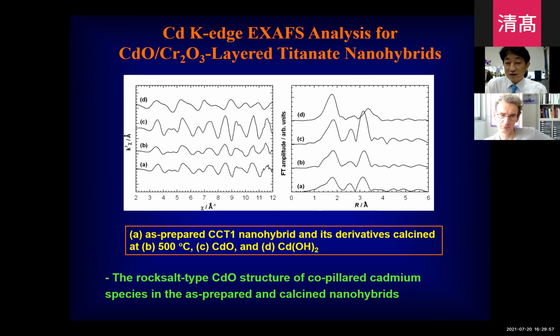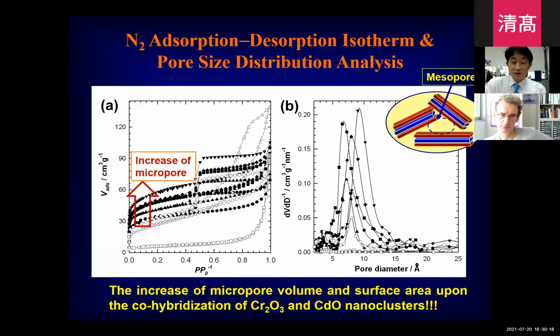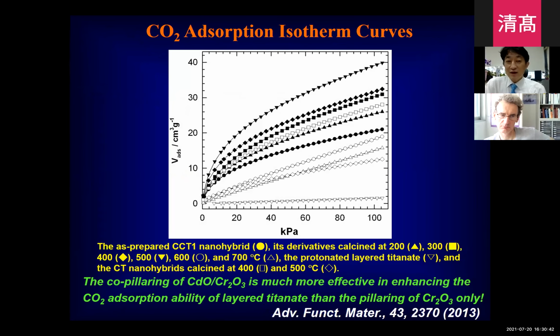Definitely, this FT structure is quite different from the cadmium K-edge EXAFS spectra. So from that, we can confirm the chromium ions just form isolated chromium oxide nanoclusters, not substituting into the cadmium site in cadmium oxide nanoclusters. So we confirm the stabilization of separated chromium oxide nanoclusters and cadmium oxide nanoclusters from the XANES and EXAFS analysis. Also, by incorporating the cadmium oxide nanocluster, we can increase the microporous volume of these materials, as you can see here. So the resulting material shows very nice CO2 adsorbent functionality. Also, it shows high thermal stability, so it is comparable to MOF, but it's much more robust.